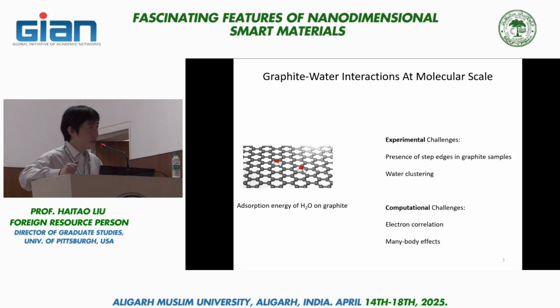Experimentally, this is also difficult to handle because water wants to cluster. So if you want to correctly measure the adsorption energy of a water molecule on graphite, you cannot just evaporate water onto graphite, because as long as you reach a reasonable surface coverage, water clustering starts to show up, and that impacts your measurement. And also, your graphite lattice is never going to be perfect. There are always defects where the preferential adsorption of water molecules would occur.